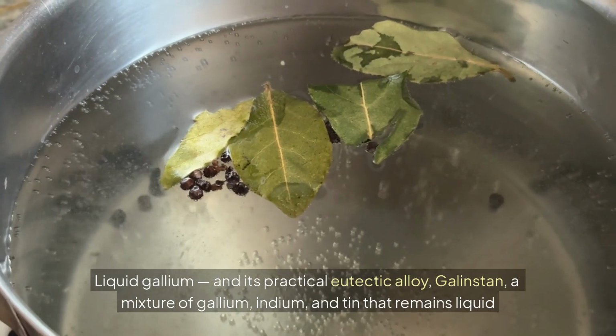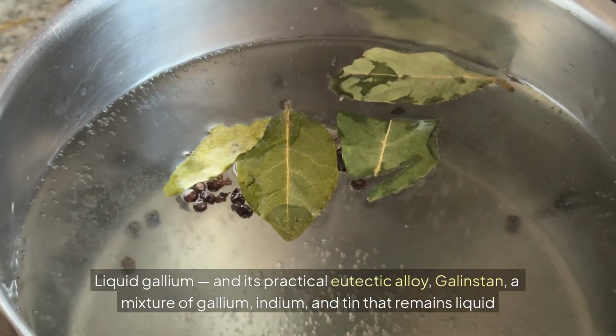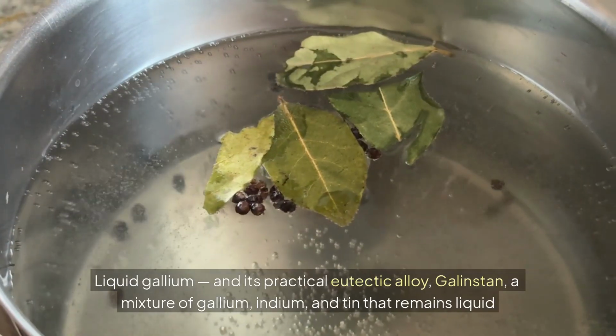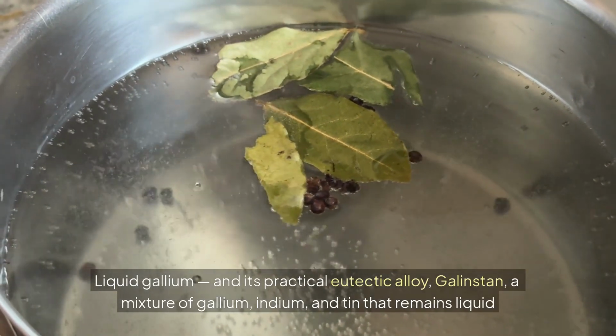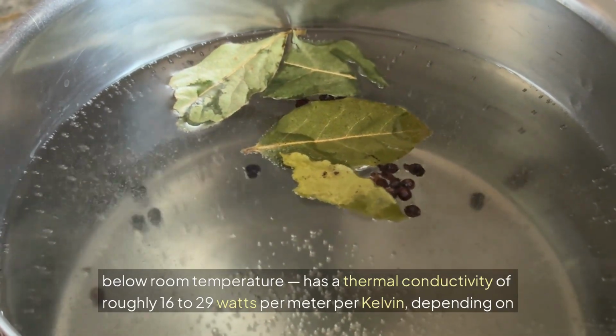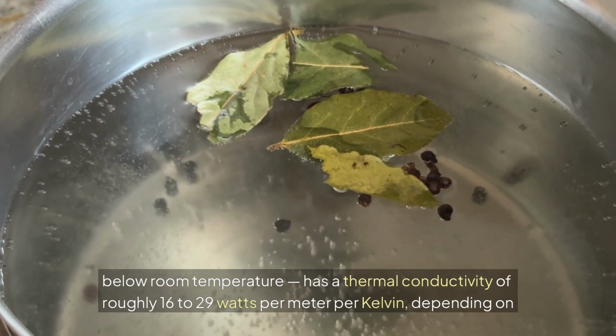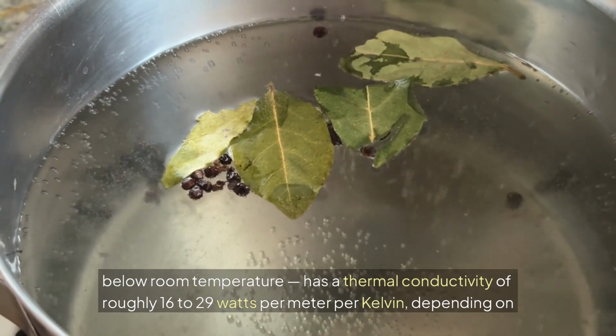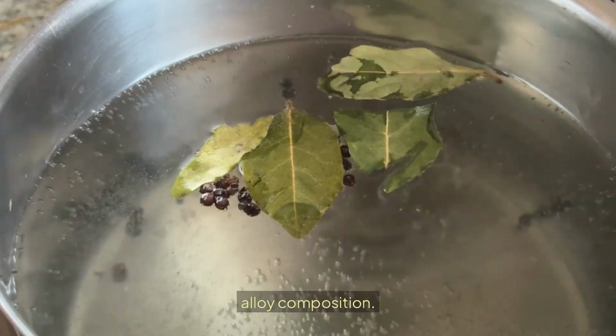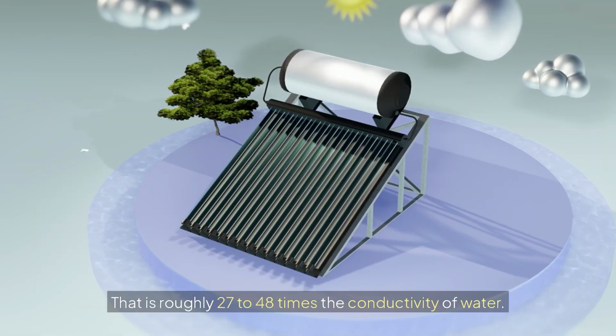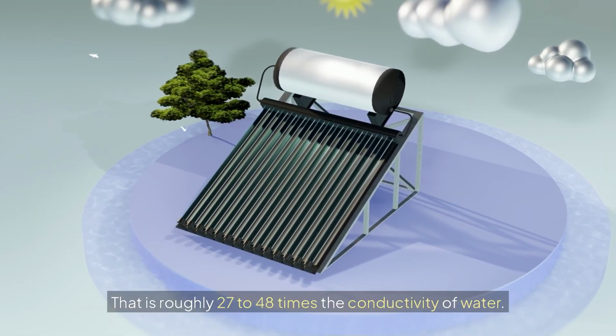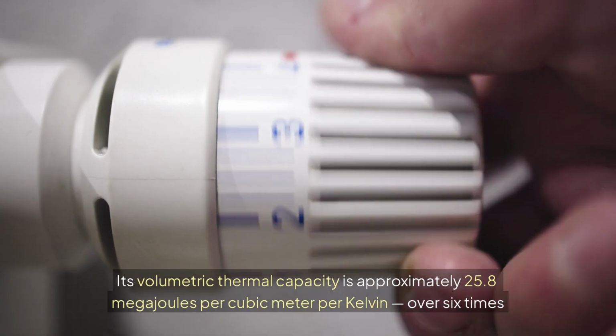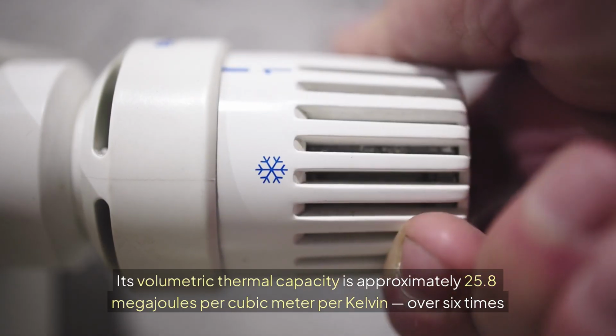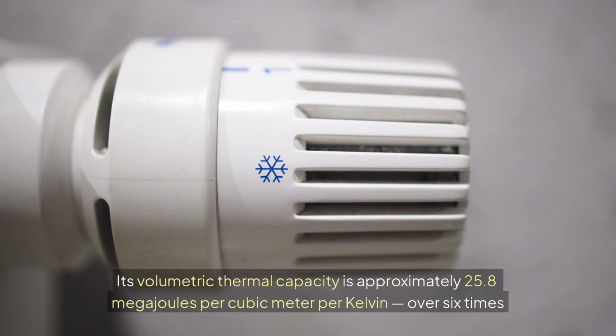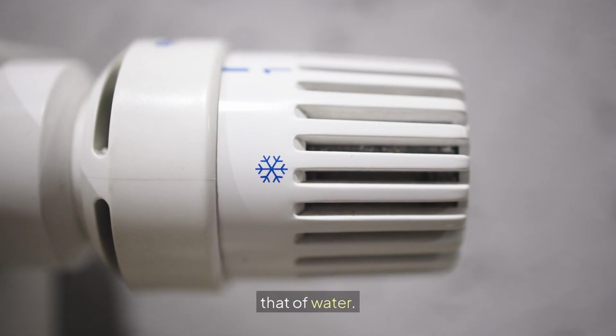Liquid gallium and its practical eutectic alloy, Galinstan, a mixture of gallium, indium, and tin that remains liquid below room temperature, has a thermal conductivity of roughly 16 to 29 watts per meter per Kelvin, depending on alloy composition. That is roughly 27 to 48 times the conductivity of water. Its volumetric thermal capacity is approximately 25.8 megajoules per cubic meter per Kelvin, over 6 times that of water.